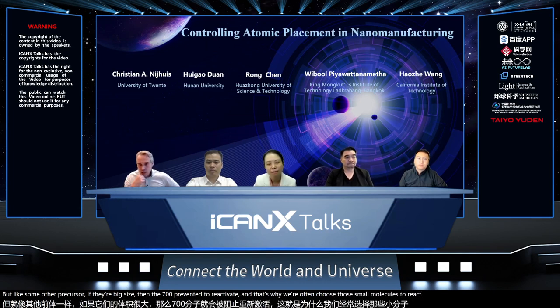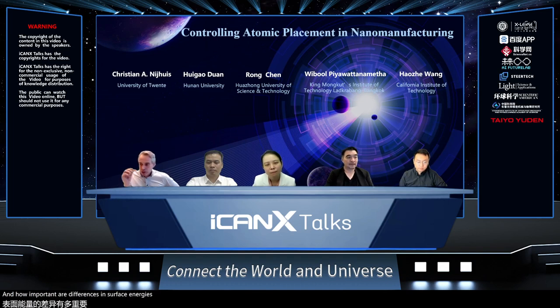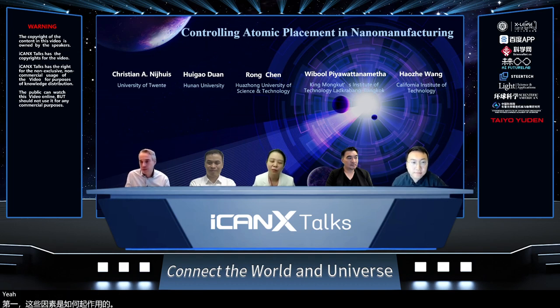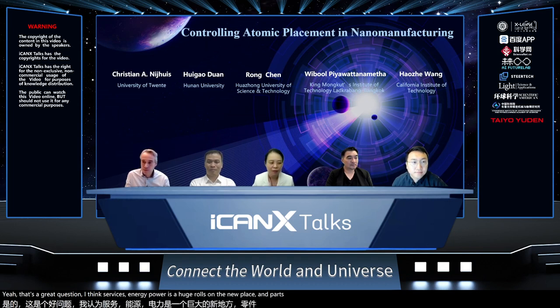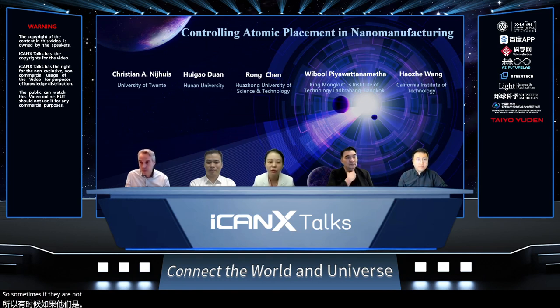Oh, wow. And how important are differences in surface energies? Sometimes you put molecules on, sometimes not. I can imagine that the incoming material will have very different wetting properties, even at those scales. I'm not even certain you can really think along those lines. How do those kinds of factors play a role? Yeah, that's a great question. Definitely, I think surface energy plays a huge role in the nucleation part. So sometimes if they are not easy to nucleate, you have to treat the surface and convert it to a lower surface energy one to get nucleation, yes. That's a perfect question.